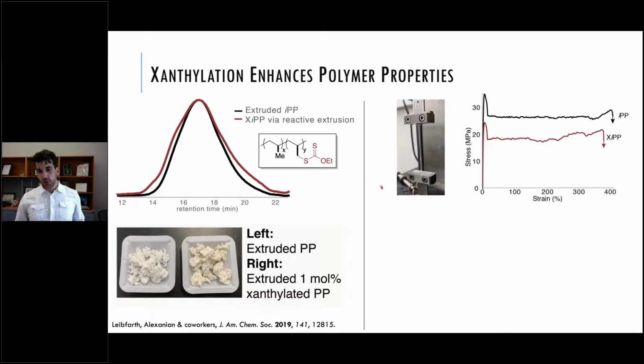The cool thing is so now we have a bunch of this material, right? We can compression mold it into a shape. We can use that shape and pull on it essentially until it breaks to do the stress strain experiment. If you look at polypropylene and our material, you can see our material behaves very similarly. You can stretch this material out to about 4 times its original length before it breaks. And the strength of our material is a little lower, but we would expect that because we added this functionality. So the strength is a bit lower, but with this functionality, again, it can now act as an adhesive or a compatibilizer much better than polypropylene.